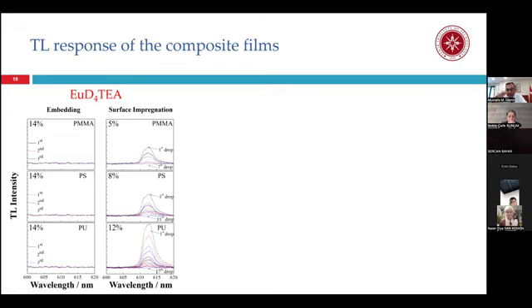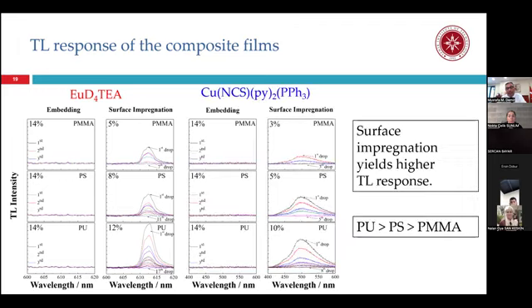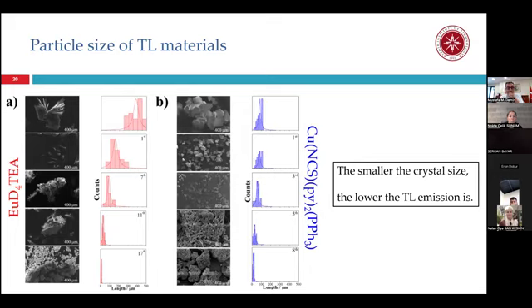The signal diminishes as the number of drops increases, and it is similar for polystyrene and polyurethane. In polyurethane, we need 17 drops to diminish the entire triboluminescence signal for the system. For the blue one, we have a similar story. Surface impregnation, as you see, yields a higher triboluminescence response, and we have a sequence: polyurethane is better than polystyrene, better than polymethyl methacrylate. You are going to see the reason in a minute.